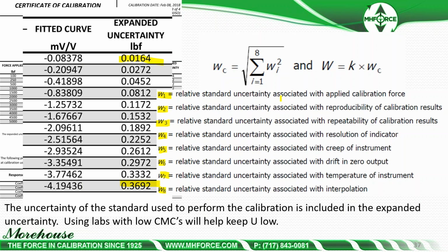It's the relative standard uncertainty associated with applied calibration force. As I said, this one's my favorite for 2 reasons, because one, the majority of the time we're using dead weights and we can give very, very low numbers. But the second is it follows that metrological traceability pyramid where the uncertainty of the reference standard must be included. And the standard does it for you. It requires it in the standard instead of outside of the standard, where you can have someone having an expanded uncertainty of 0.05 giving you measurement uncertainty of less than that when you just use the ASTM lower limit factor only.